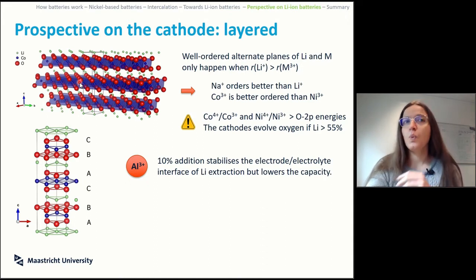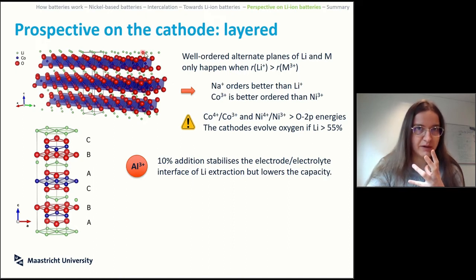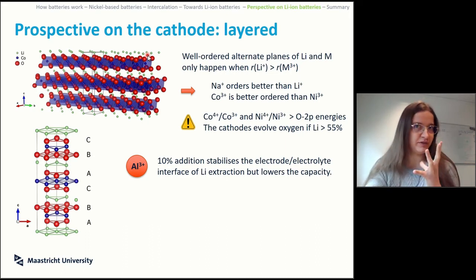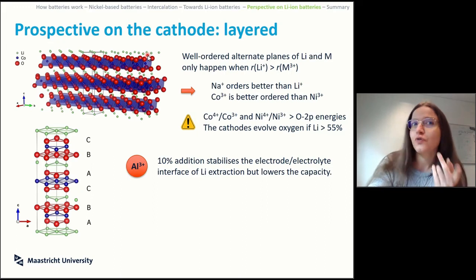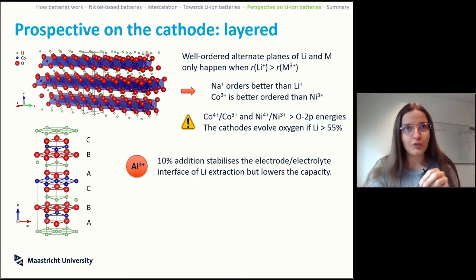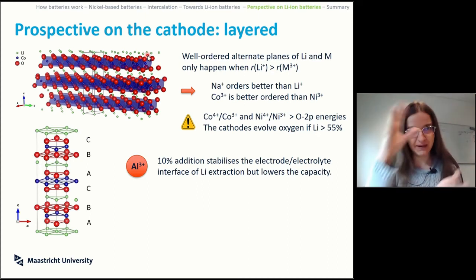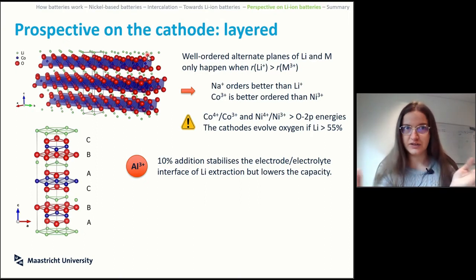And you need to remember that once you take lithium in and out of your structure, so you have your lithium, your oxygen, your metal, depending on how big the affinity of your transition metal is for the other coordination state, when your cathode is almost completely discharged and there are a lot of vacancies in the states in between where lithium will be, it could be beneficial for the structure, not for you, for the metal to occupy this empty tetrahedral site. And if the metal goes in there, then you change the coordinations completely and you might have distortions within the structure.